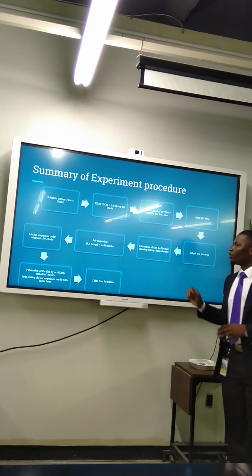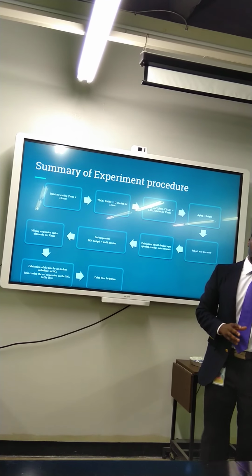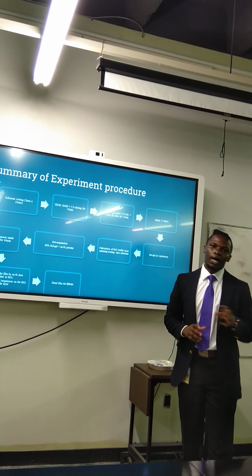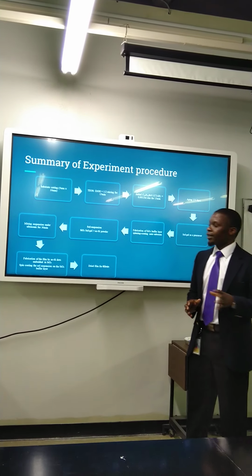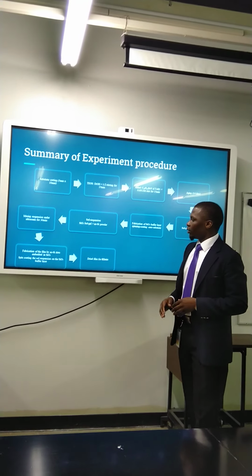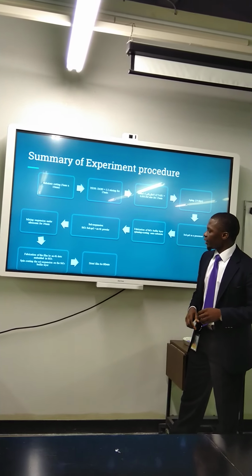And later on, we made the sol-gel suspension by adding silicon dioxide solution or sol-gel with nanocrystal powders. And then we mixed the two under ultrasonic for 30 minutes, and then we fabricated the thin film, nanocrystal silicon dots. And then the thin film was dried for 60 minutes.